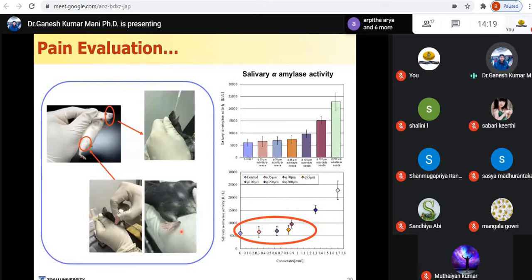So initially we started the experiment with mice. You can see the microneedle, we are puncturing it onto the mouse's leg, and immediately after puncture we take the saliva, and then we do the alpha amylase test, checking how much alpha amylase is present in the mouse saliva before and after injection, and then we analyze it. What we found is that this microneedle, which mimics the mosquito, has lesser alpha amylase activity. That indicates that the mouse is not stressed much, so it did not feel much pain compared to the normal needle.